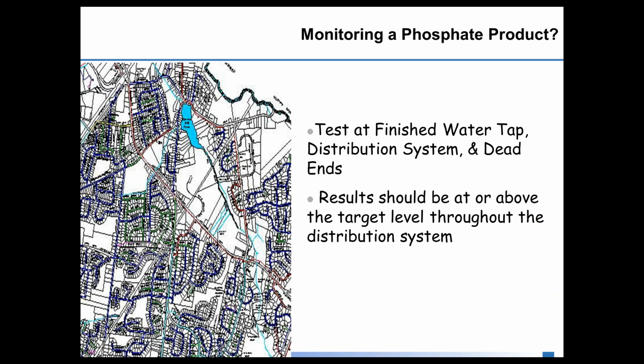Typically, for a customer that's feeding a phosphate product, we'd ideally always love to see orthophosphate tests at the finished water tap at the treatment plant itself. We'd love to see some samples out in the distribution system at multiple points so you have an idea of what the orthophosphate level is in the distribution system. And then we want to focus on places where you have issues or dead-end lines, where you might see a drop-off in residual or chlorine or other water quality parameters, and see what the levels of orthophosphates are at that level.